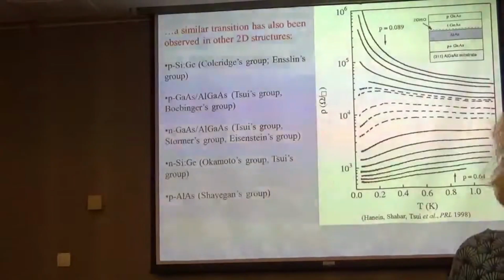A Canadian group, Peter Coleridge's, observed the same effect in a different system. And maybe people started to say, oh, maybe indeed something strange is happening in silicon. Then an Israeli group, observed it in gallium arsenide. Here is a picture, it's very similar to what we see. And then it turned out suddenly that it exists everywhere. Once you take a clean sample, you can see this effect everywhere. So this paradigm, almost 35 years old, but at that time 25 years old, turned out to be completely incorrect. It's obviously correct for non-interacting electrons. But once you make electrons interact by reducing electron density, you can see this effect everywhere.